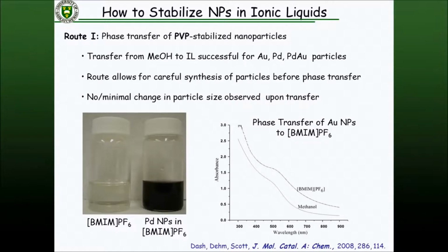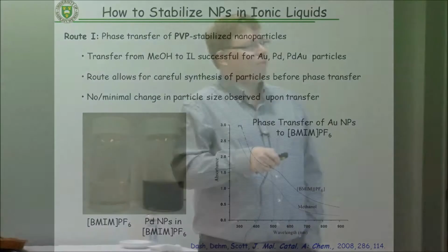Of course, you have the polymer in there as well, so maybe not quite as intricately beautiful, but nevertheless, we do get minimal change in the particle size upon transfer of particles from one solvent to another. And we can do this for things like palladium, which is a very well-known catalyst. We can do things like gold, and you can see that we get very, very small changes in the plasmon band of gold particles as we transition the methanol to the ionic liquid.